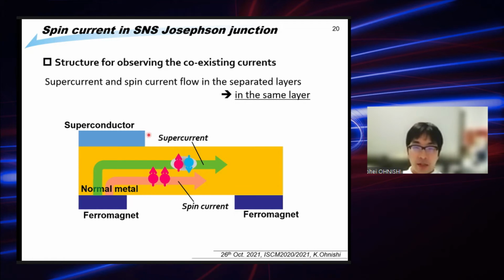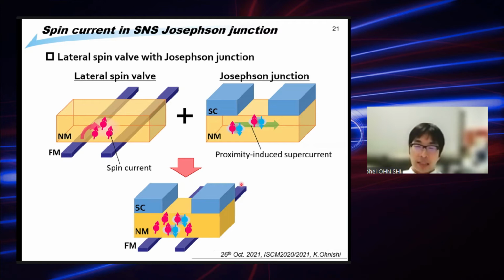Okay, so to confirm that these two currents can flow in the same layer, we can remove the superconductor in the top layer. By this, these two currents should flow in the same layer, but in this case, by just removing this superconductor part, we cannot measure the supercurrent. So we add another superconducting part here. By this, we can observe the supercurrent in the normal metal layer. This is because the structure is a combination of the lateral spin valve and Josephson junction.